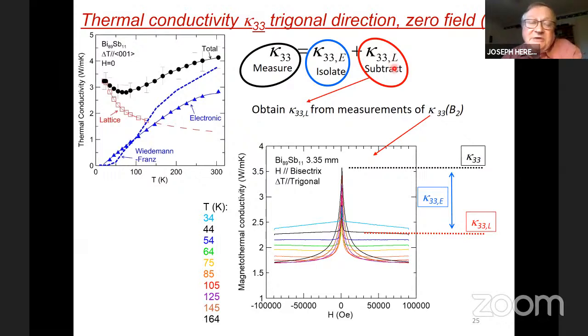But of course, in order to make measurements and calculations, we have to subtract this lattice part. So how do we do that? Well, we take the same sample, but instead of putting the field along the three direction, B3, we put the field transverse along the B2 direction. Then we create a large magnetoresistance. And so the thermal conductivity starts here. That is a sum at zero field, a sum of electron and phonon part. And then when we apply the magnetic field, we freeze the electrons out by the magnetoresistance, and we are left with only the phonon part.